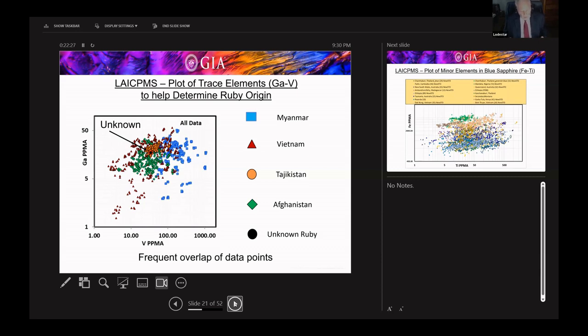It'd be nice if the data points plotted in different areas of this graph. But you see, there's oftentimes a frequent overlap of data. How do we address that? Well, there are a couple of things we can do. Maybe we can pick different pairs of elements, or we can graph elements 3 at a time on a triangular plot. There are a lot of these graphs produced, looking for hopefully a clear indication of where this unknown ruby comes from, compared to rubies of known origin we've also analyzed that are in our database.